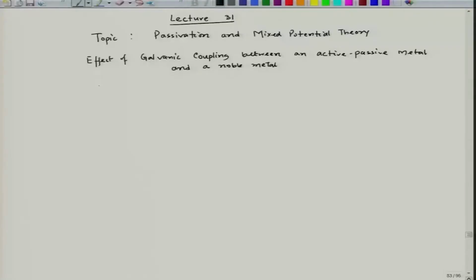And we have also understood this particular increase in corrosion rate of the active metal with the help of mixed potential theory. And if you recall, we have seen the plot in case of, let us say, zinc connected to platinum. So, this is E, this is log I, and this becomes my active zone of zinc, so this particular point is E equilibrium and I naught of zinc.